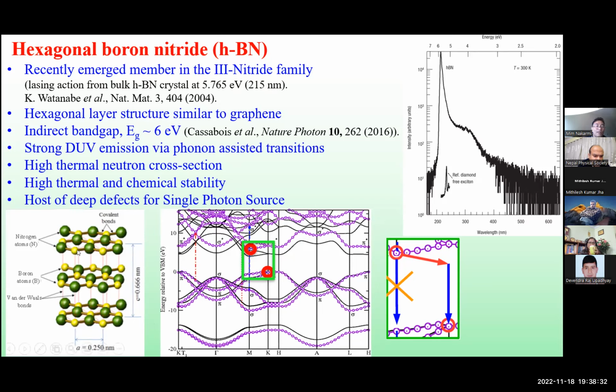So graphene is made entirely of carbon. All carbons are sitting in the hexagon, and one layer of that is graphene. Similar to graphene, in boron nitride, boron and nitrogen are sitting in the hexagons, and those layers sit layer by layer, bonded by van der Waals force. But the hexagons are bonded by covalent bonds, and its band gap is about 6 eV. Other properties are high thermal and chemical stability, and it can also be used as a neutron detector because it has a high thermal neutron cross section.